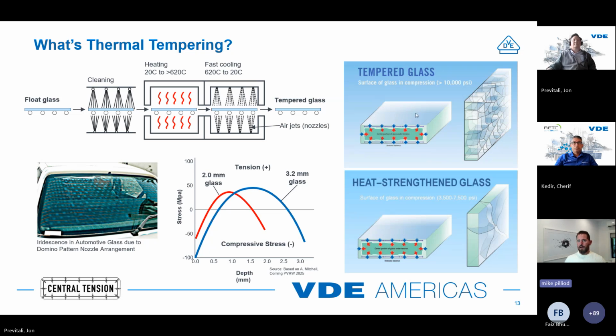One of the things that I do want to highlight here is that within the glass tempering world, this is not a binary tempered glass or heat strengthened glass. Those are historical things from the architecture safety glass world. This is a continuum of how much surface stress you have and how deep the depth of layer is. For instance, what's considered heat strengthened glass in the industry ranges from 3,500 to 7,500 psi. There's a significant difference between those, as well as it's a continuum.